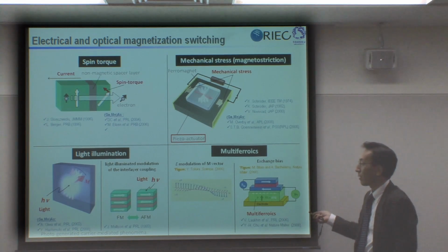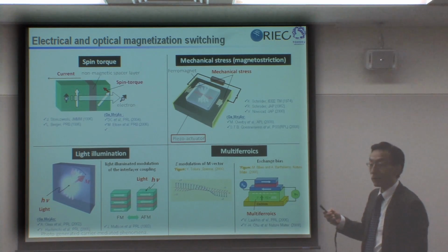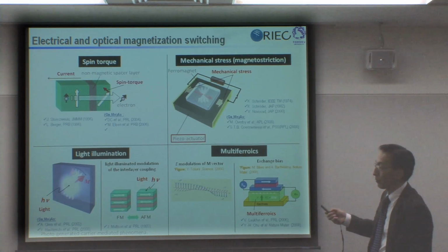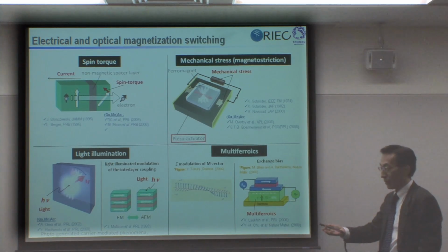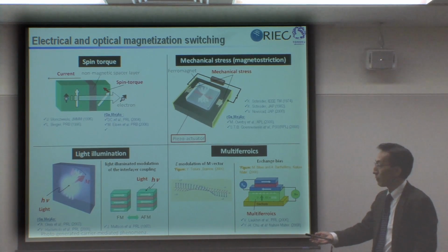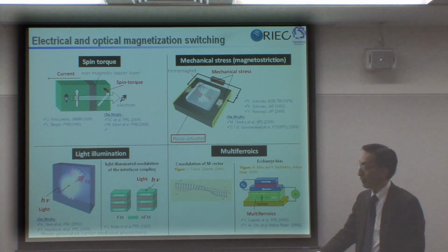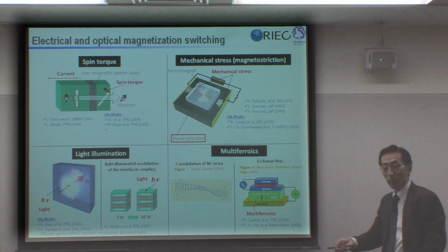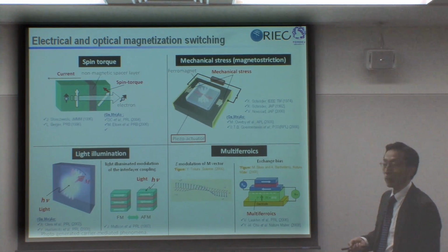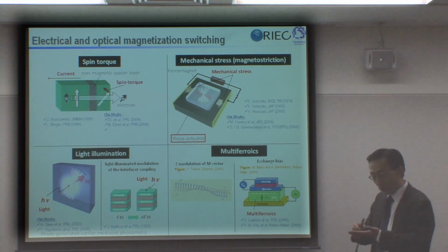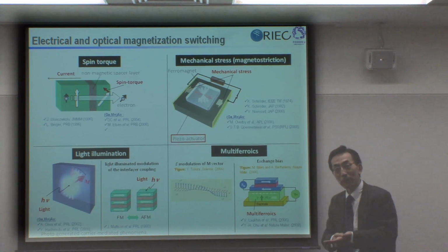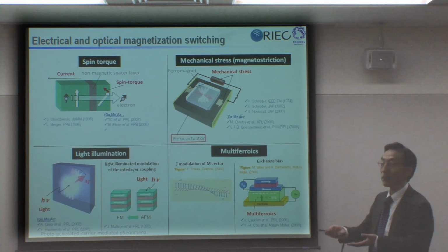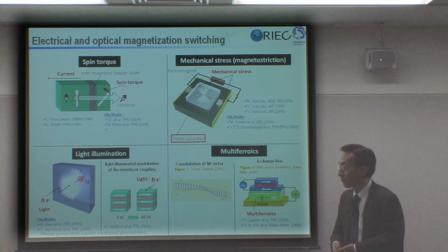Apart from very fine physics that is being done in multiferroics, one of the goals for multiferroics is to switch magnetization direction by electrical means. But here I have shown you that there is another approach, that you can change the carrier concentration, and with this you can change the anisotropy. And if you can control the anisotropy in an electronic way, we might be able to get switching. You might think that this is a low temperature measurement. We are using gallium manganese arsenide. So what about room temperature? What about other, let's say, ordinary materials?